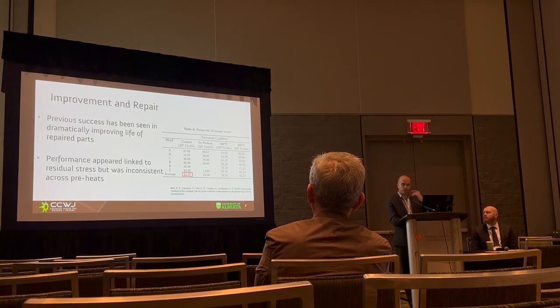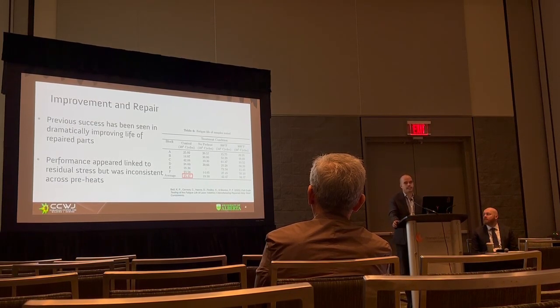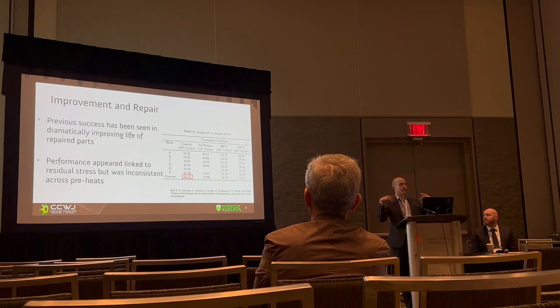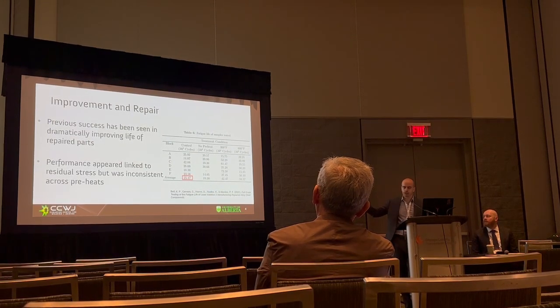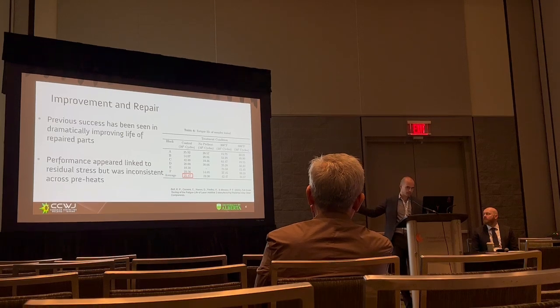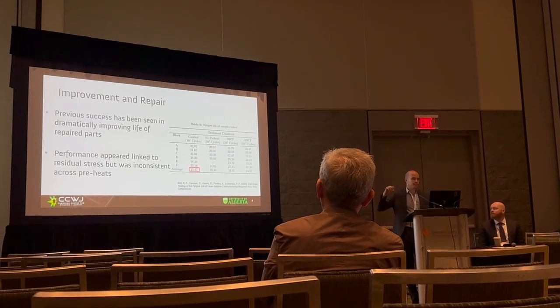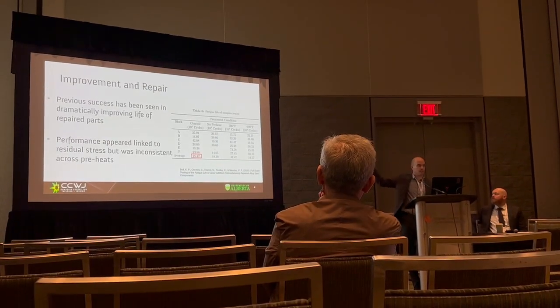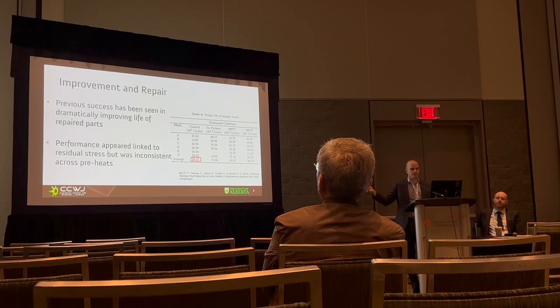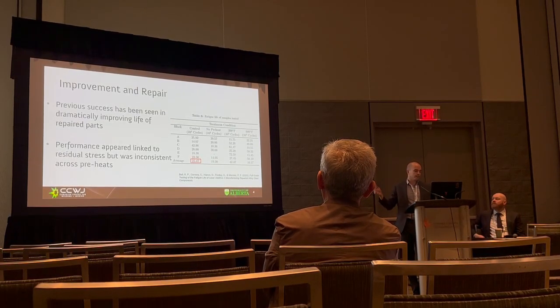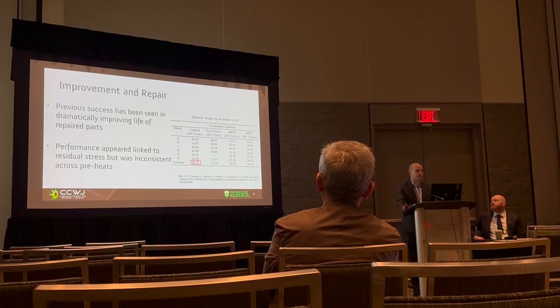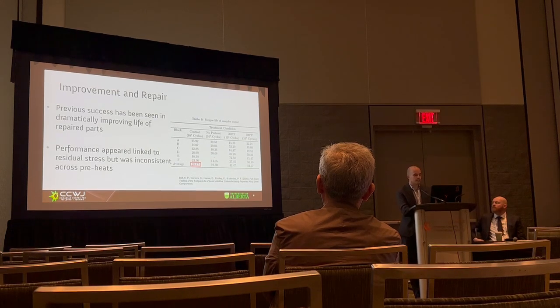So what you're looking at here in this table is a set of fatigue test results. They put it on a rotating bender, ran it till failure. So the numbers at the bottom, we're not going to worry too much about the specific numbers, we're just going to look at magnitudes. But basically the number at the bottom is 25 times 10 to the 4. It's the number of rotating bend cycles to failure for each part. So that first one I just boxed is the control. That was the as-cast part from the manufacturer, its lifespan.